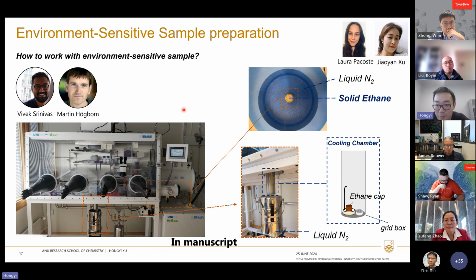We have to make sure that the sample does not see air during data processing, during the sample preparation, right? So we actually borrowed a glove box from Martin's group, and then we crushed the powder in the glove box in nitrogen environment. And then for this glove box, there's a special attachment, which is a cold trap. So we can actually have solid ethane transferred into the glove box and being kept cold before the plunge freezing. And then we can take it out and then defrost the solid ethane to make liquid ethane, and then plunge freeze our grid into the liquid ethane, and then cryo transfer the grid out of the glove box.